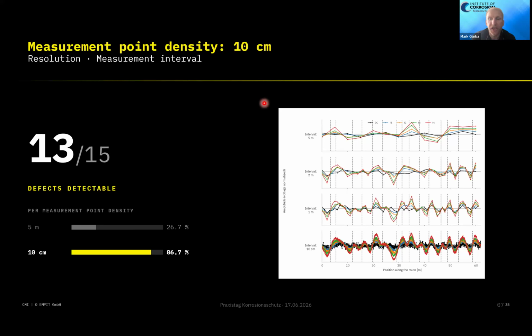So defects which are not corroding have an enhanced pH value, let's say above 9. And they will have nice amplitudes in your signal, because we know when you measure with your gradient, pH value goes up, spread resistance goes down, gradient goes up. So they are beautiful, cathodically protected defects. But we are actually interested in the defect where pH value is low if we are in the DC regime. So let's say near neutral, where we know spread resistance is possibly higher because of the lower pH value and your gradient is really small.